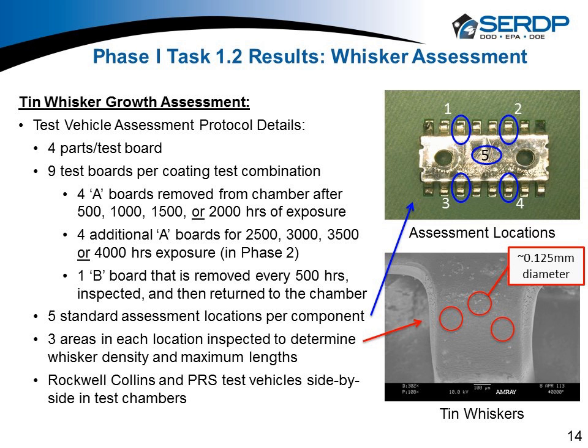We kind of teamed up. We wanted to see, one set of these specimens was every 500 hours going in and out of the humidity chamber. We'd take them, look at them in the SEM, put them back in the humidity chamber, but that's about 24 hours of exposure. Did coming out of the chamber change the behavior? So we had a set of specimens that we pulled out, we inspected, and never went back in. So those were staggered such that we would accumulate 500 hours, 1,000 hours, 1,500 hours, trying to look to see